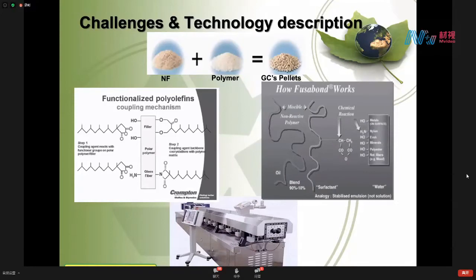We use some methods for modification of the surface, because the natural fiber itself is hydrophilic, so it's like water, and the polymer is hydrophobic. To combine these, we have a challenge to modify the surface of the natural fiber. So we use some compatibilizers or functionalized polyolefin as a coupling agent to make good wettability and good compatibility, giving a strong bond between the fiber and the polymer chain.